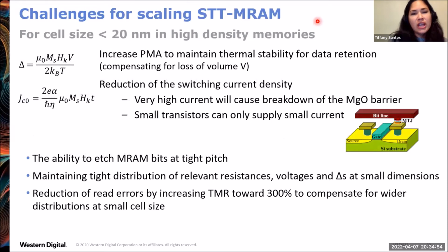Okay, so the challenges for scaling to smaller cell sizes, 20 nanometers or less, is that by making smaller bits, you lose thermal stability because of this loss of volume V. So to compensate for the loss of thermal stability due to small cell sizes, you need to increase the perpendicular magnetic anisotropy, but at the same time, keep your switching current density low. So you want to keep the switching current low because very high currents will cause breakdown of your MgO barrier, but also in a high density memory, you're going to have a high density of transistors. They're going to be very small, and small transistors can only supply very small current, but yet that current needs to be large enough to switch your MRAM. Okay.